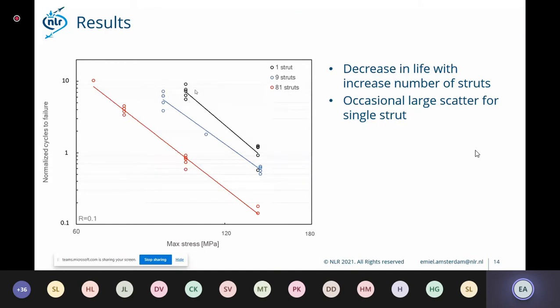But these are the results for the single struts, and we see that the results for the 9 struts specimens are decreasing, which is quite a remarkable result. So if we increase the number of struts, the life decreases, and if we go to 81 struts, it decreases even more, while the load on all the specimens and the cross-sectional area is the same as I mentioned before.